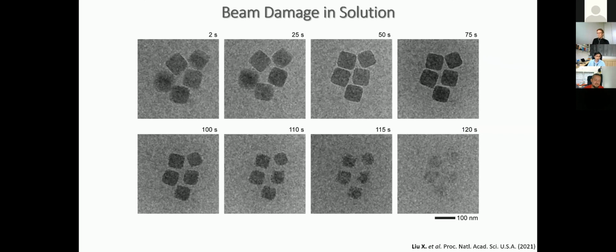And in this experiment, I'll show you in a bit what the dose is, but you see they disappear quickly, right? So typically we will need like 50, 60 seconds to see the phenomena, but at 100 seconds they're already disappearing. So I would assume at 50 or 75 seconds the damage starts kicking in. So disappearing means everything is falling apart, right? If you're a car, your wheels are coming out, the doors are falling apart. But damage probably happens much, much earlier, right? So we have to be very, very careful about the doses we use.